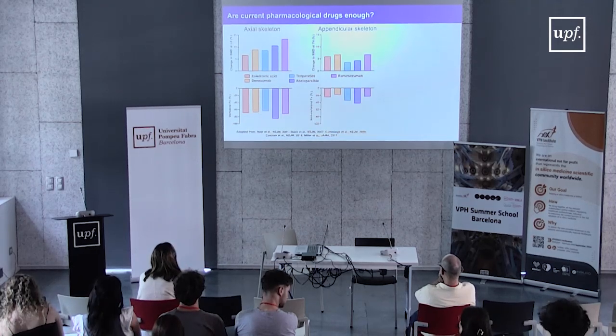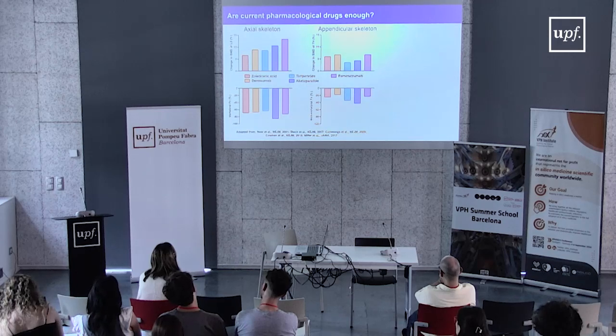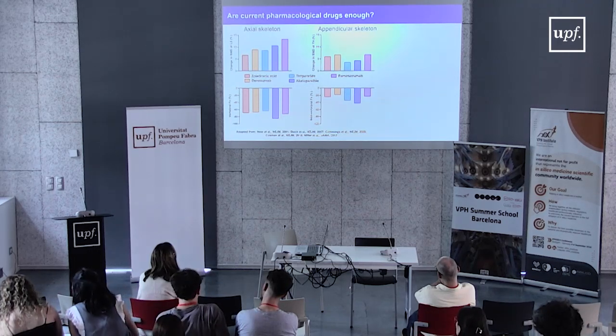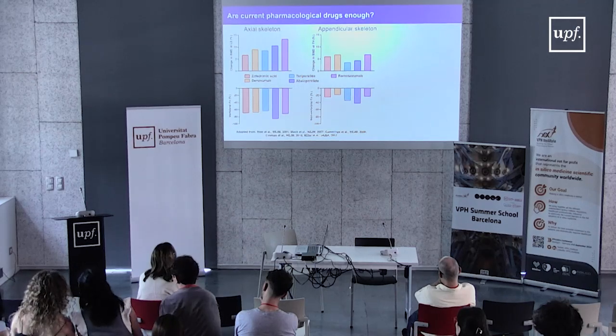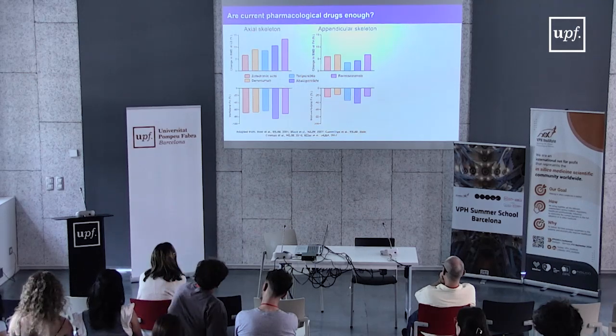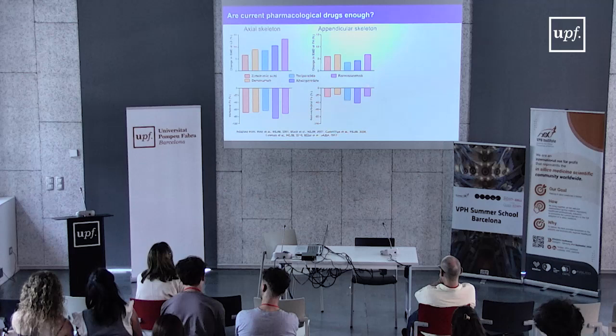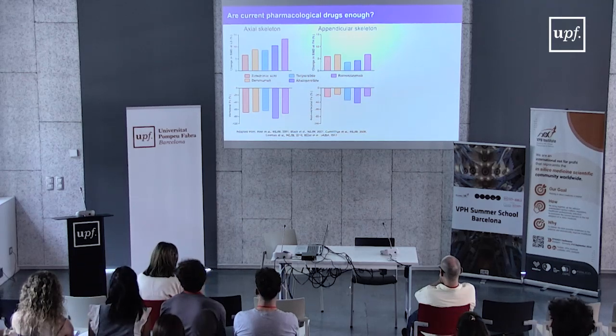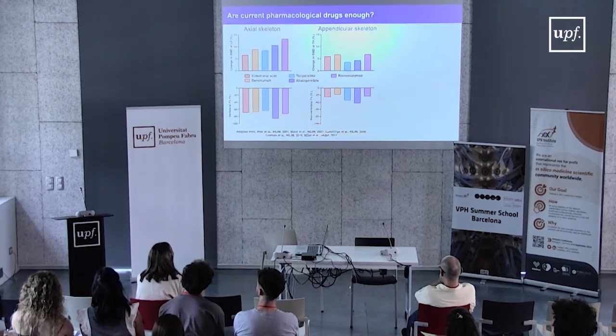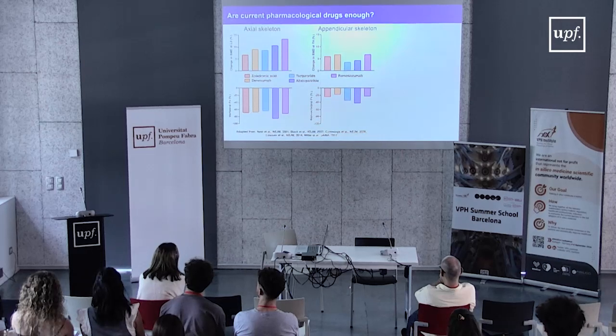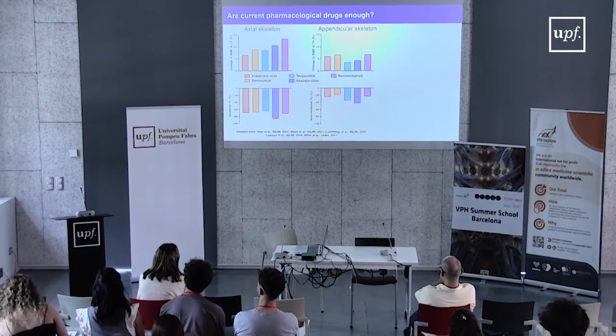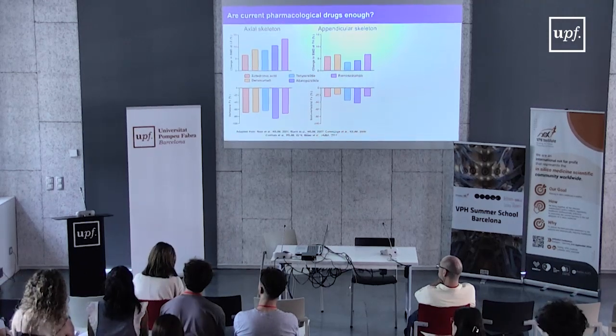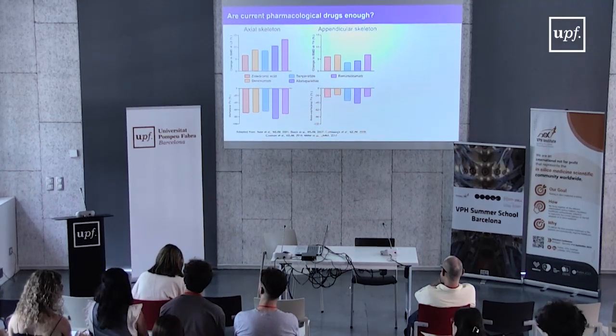The problem arises on the appendicular skeleton, and especially the femur, because by increasing the bone mineral density, already you can see that bone mineral density cannot be increased at the same level as in the lumbar spine by the same molecule. And by increasing the quantity of bone, you reduce only by 20-25% the risk of developing a fracture. So 75% of patients taking these anti-osteoporotic drugs will still have a second episode of osteoporotic fracture.